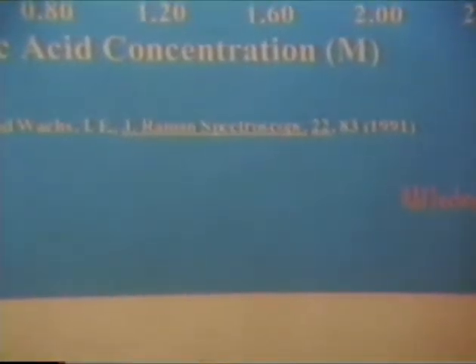Again, this is some work of Wachs. Looking at the solubility, you can see that there is a very rapid rise in solubility if you add niobium oxalate to aqueous oxalic acid solutions. So ultimately, with something like a 0.8 molar solution, you can achieve concentrations of about 30 weight percent niobium oxide, but you've got to use oxalic acid solutions.